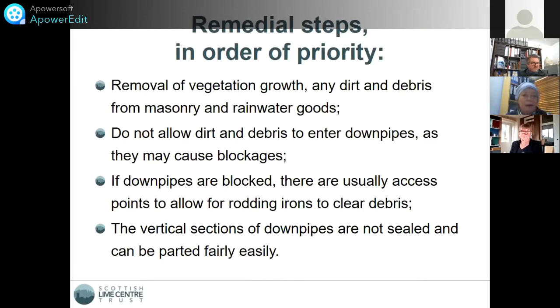So in terms of remedial steps, in order of priority, removal of vegetation growth, any dirt and debris from masonry and rainwater goods is paramount. When you're clearing out gutters, don't allow any of the dirt and debris to enter downpipes, as that might cause blockages. If downpipes are blocked, there's usually an access point along the downpipe to allow for rodding irons to clear out debris. And the vertical sections of downpipes are not sealed and should be able to be parted fairly easily.